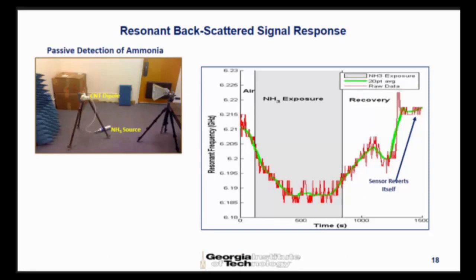So I extracted the resonant frequency from the dips in S11 and plotted the resonant frequency as a function of time for various gas exposure cycles. So for the first 5 minutes, there is no gas. For the next 10 minutes or so, there is gas, and then I remove the gas. So what happens is there is a downward shift of resonance because of the gas exposure. And when the gas is removed, it comes back to normal. So the sensor reverts itself. This is the same phenomenon on carbon nanotubes which many other researchers have observed, this reversibility. It's very encouraging that our results are following the same pattern.